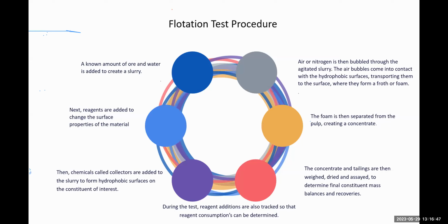Creating a concentrate. The solvents, and then you have your main tailings. The concentrate and tailings are then weighed, dried, and assayed to determine final concentrate, mass balance, and recovery. So after then you weigh and analyze your concentrate and your tailing to check your recovery. If much of the lithium has been in your tailing, then it means your process is not efficient. So you have to go back to your process control or your chemical engineering and check what is wrong.